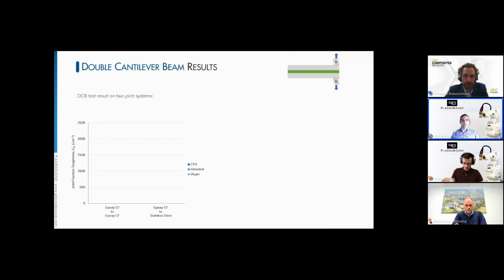But when we look at the double cantilever beam, which is more common in the aerospace industry, but is starting to become more prevalent within other industries as well, because it's an understanding of the quality of the bond and the amount of energy or toughness within that bond. On the top right, there is an illustration of a DCB where you have a pull-out block, you have two long adherends and the adhesive down the middle, and the intent is these will pull apart and a crack will form down the middle of the adhesive or on the substrate itself.